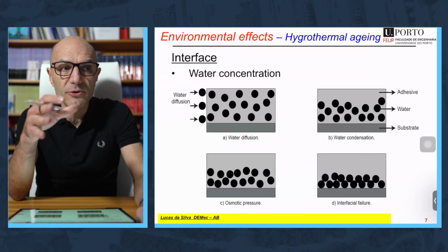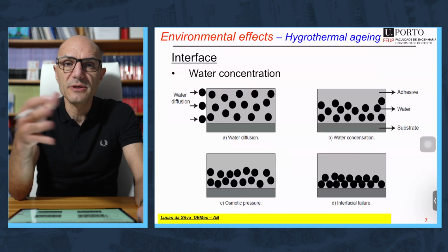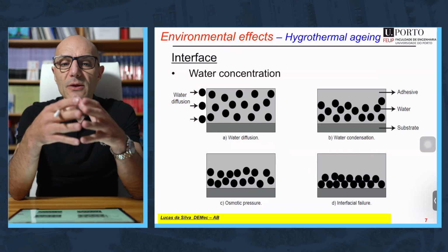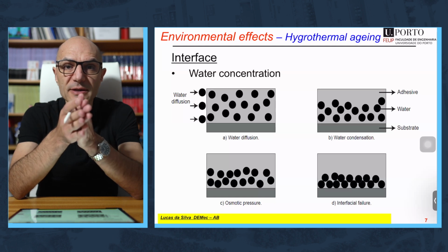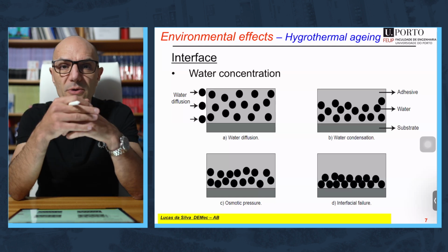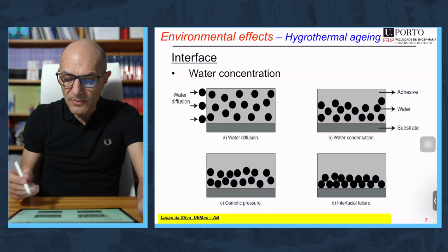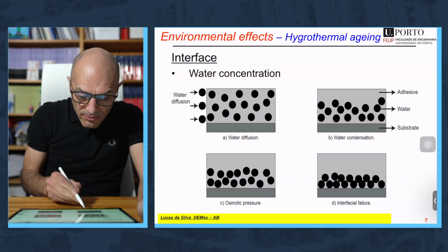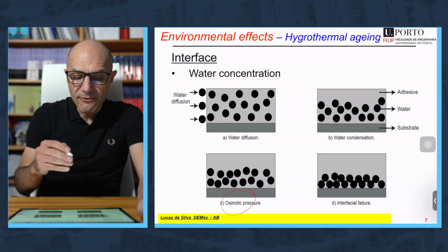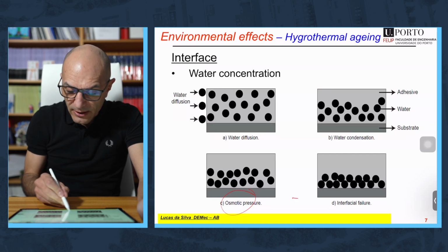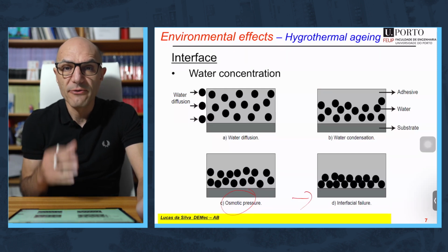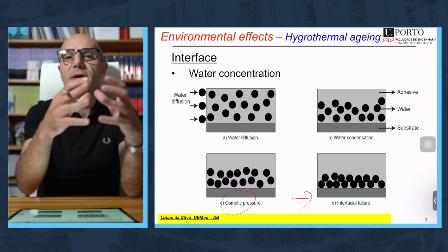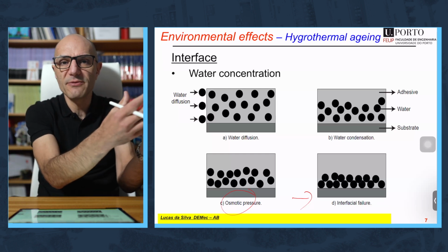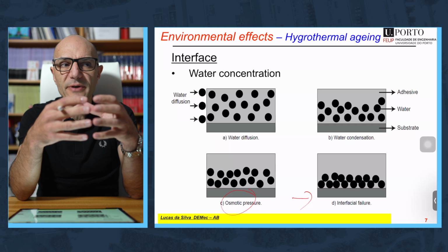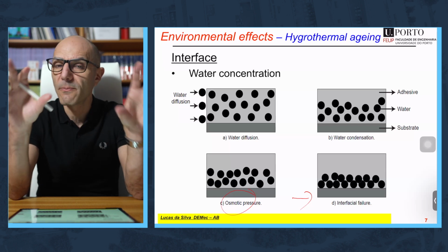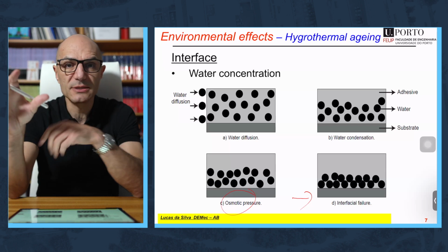Another thing that typically occurs when you have the joint in contact with water is that the coefficient of diffusion at the interface is much faster. You have a concentration of water at the interface, and this might cause osmotic pressure due to the variation of water concentration and cause eventually interfacial failure. So as you can see, one thing is the effect of water in the bulk adhesive material. Another thing is the effect of water at the interface. It's two completely different things, and it's much worse at the interface.